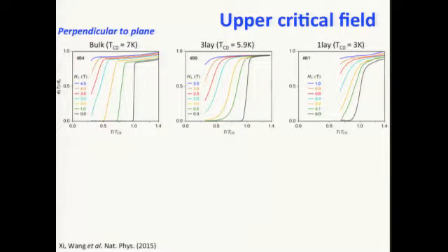And the other observation, which is somewhat surprising, which I'm going to spend the rest of the talk explaining, is the measurement of the upper critical field in this material. The upper critical field is essentially the highest magnetic field at 0 temperature that quenches superconductivity. I present a measurement of the bulk material, 3-layer material, and monolayer material under perpendicular magnetic field, perpendicular to the plane of the material. You can see that superconductivity gets quenched by about a few Tesla.